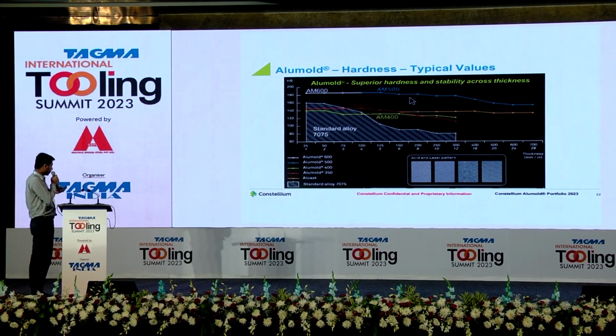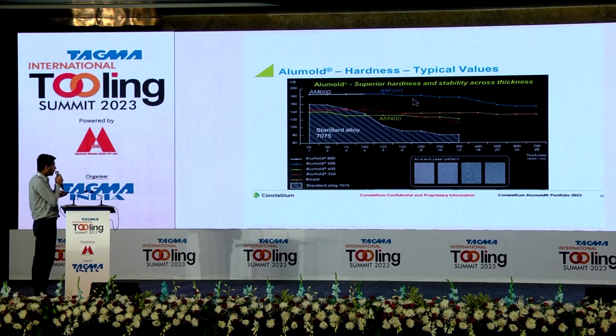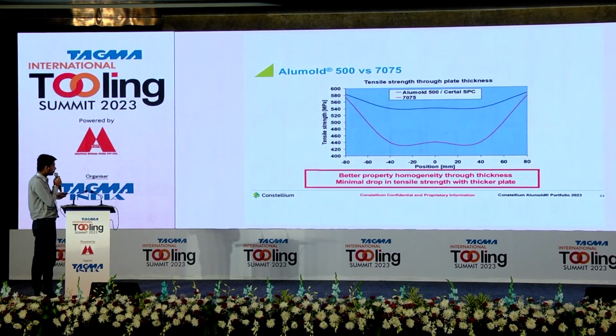Yeah, this is a typical example of that. Standard 7075 is dropping, whereas Alumold 500 is stable throughout. This is considering a plate of 160 mm thickness. In 7075, the mechanical properties reduce toward the core of the block. But for Alumold 500, the mechanical properties stay uniform.